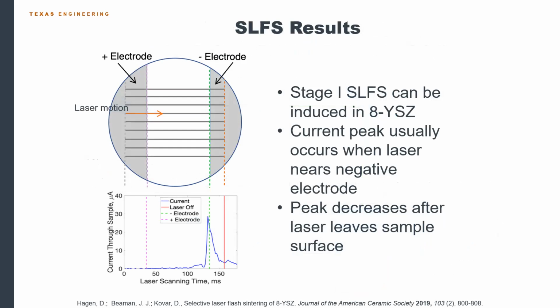I'll give a more detailed view here. The image on the top is a top-down view of the powder bed. The gray regions are the electrodes, the white region is the loose powder, and the laser is indicated by the orange arrow. The laser starts scanning in the positive electrode. The plot below is the current through the part or powder bed as a function of time. You can see as the laser starts scanning on the positive electrode, there's no current flowing, and it continues on into the powder bed. There's still no current flowing until just before it reaches the negative electrode. And then you see this sharp spike in current. And this is kind of the hallmark of successful laser flash sintering.